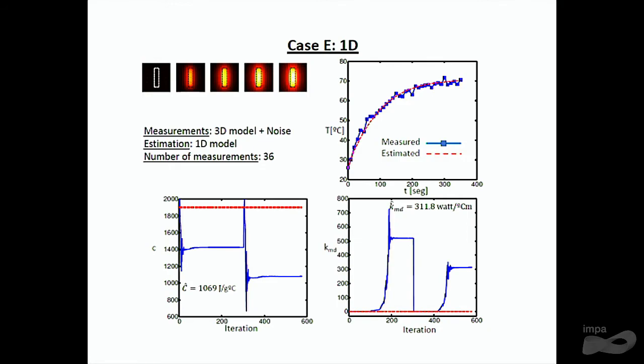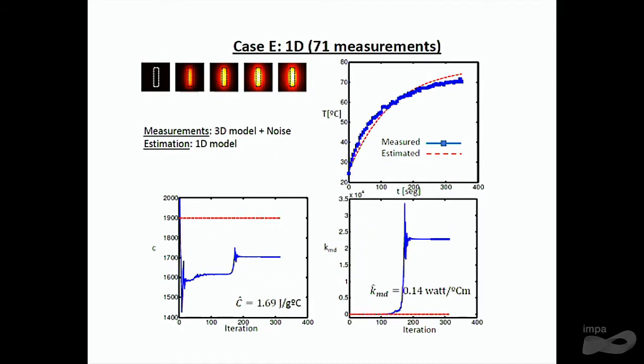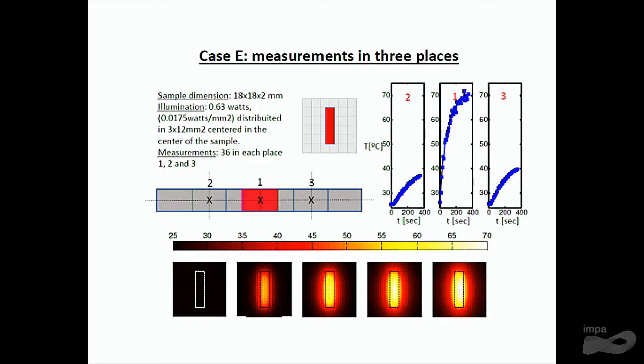So we have done this with all the cases, but because I have little time, I want to go directly to a case in which we have improved even more the behavior of one of the reduced models. We have added to the measurement I mentioned before 2 more measurements at different places in the sample. The places are in a cross section of the sample, in the middle of it, and in the middle of the thickness. That is 1, 2, 3. These are the places where we measure.